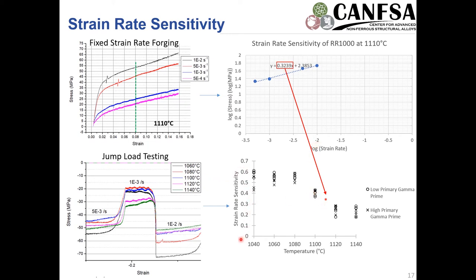And what's interesting about this is that high strain rate sensitivity is an indication of superplastic deformation occurring. And as we approach higher temperatures, we see this decrease in strain rate sensitivity. We believe that this is because as we're approaching the gamma prime solvus, we're dissolving the gamma prime and increasing the gamma grain size. So it's lowering the propensity for superplastic deformation. And this is interestingly the critical regime where abnormal grain growth is occurring.